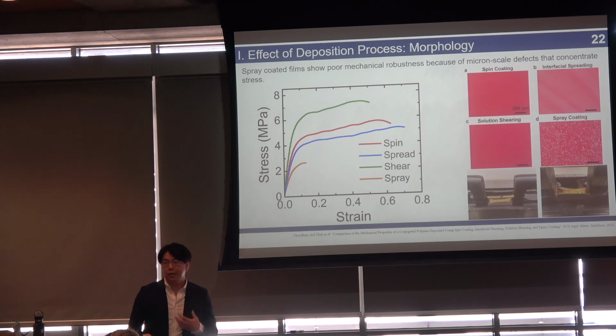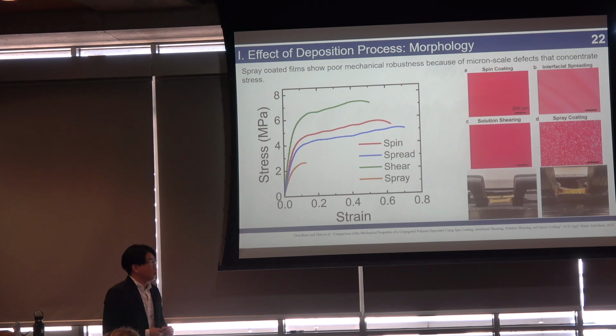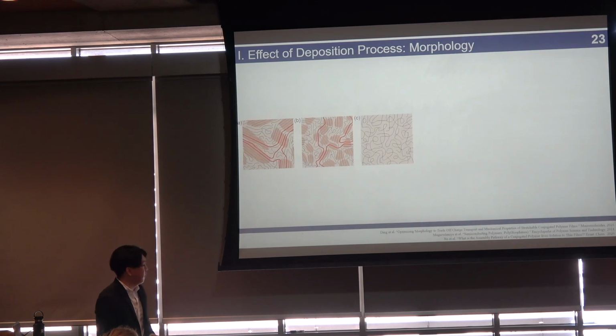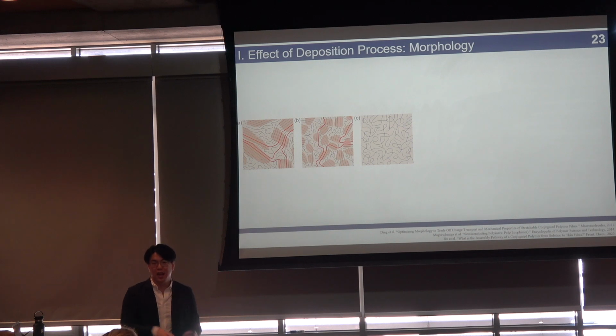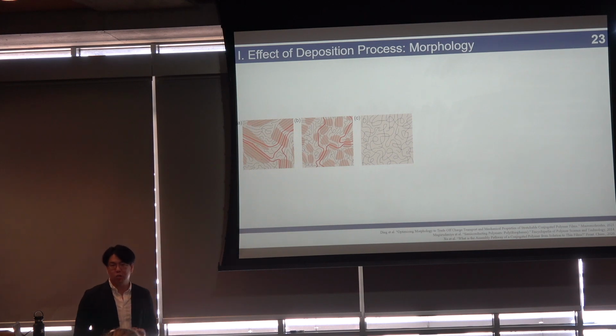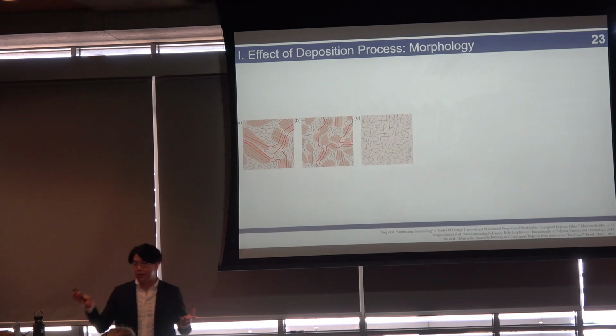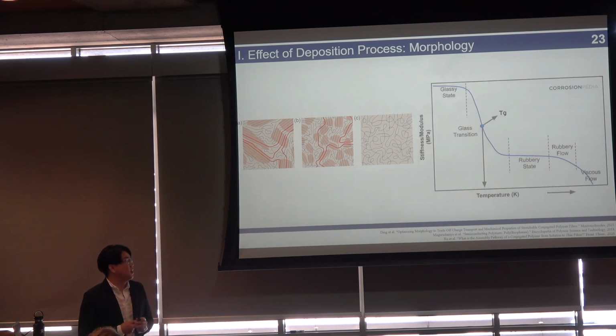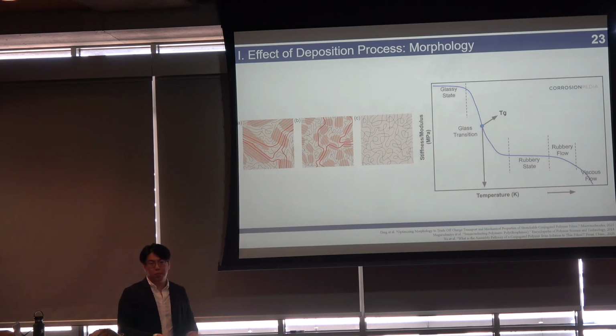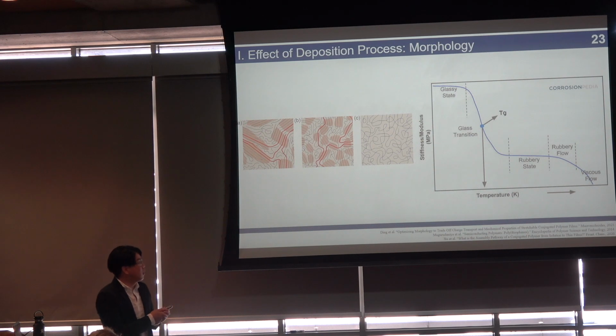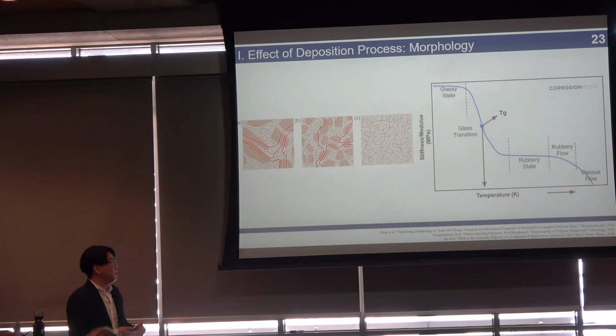To look at why the other films behave the way they do, we can actually look under the hood of the car, and we can look at the morphology of our polymer film. So these polymers are semi-crystalline polymers, and what that means is they have crystalline or ordered domains and amorphous domains. You could think of semiconducting polymer films as having a morphology that resembles spaghetti and meatballs, where you have a bunch of free-floating spaghetti polymer chains in the amorphous domains, and your meatballs are very ordered crystalline domains. And because of this amorphous and crystalline structure, polymers have something called a glass transition temperature. So much like water boils into water vapor at 100 degrees Celsius, the glass transition temperature is the transition between the glassy state of the polymer and the rubbery state of the polymer.